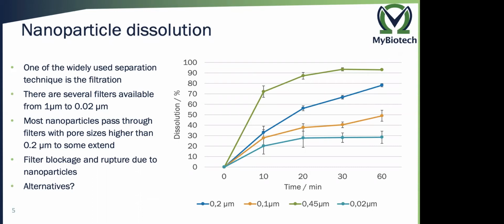If you go below 0.2, there are filters, for example, 0.1 micrometer or 0.02 micrometer, which is theoretically able to filtrate the nanoparticles. But depending on the concentration of nanoparticles in your dissolution media, it might be that you will get filter blockage, and at the end of the day, filter rupture due to the nanoparticles. So we started looking for alternatives.